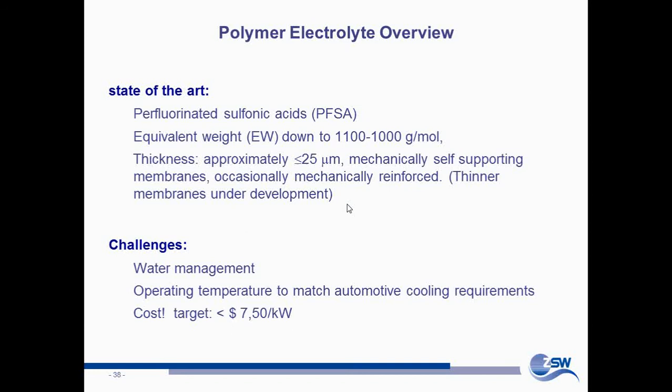Now, the state-of-the-art perfluorinated sulfonic acid membranes don't become chemically unstable at 90 or 100 degrees. They just change their degree of hydration, and they're losing water pretty fast.